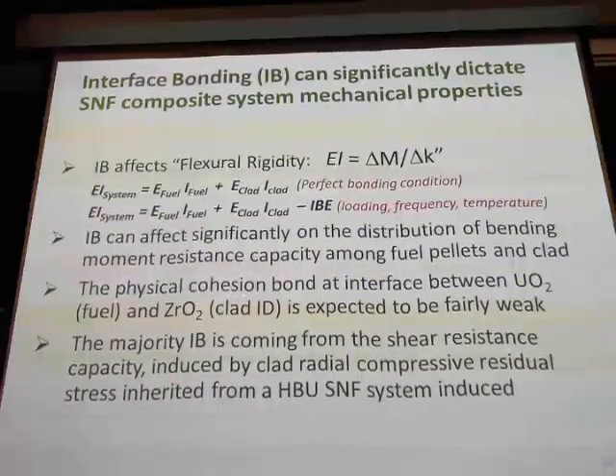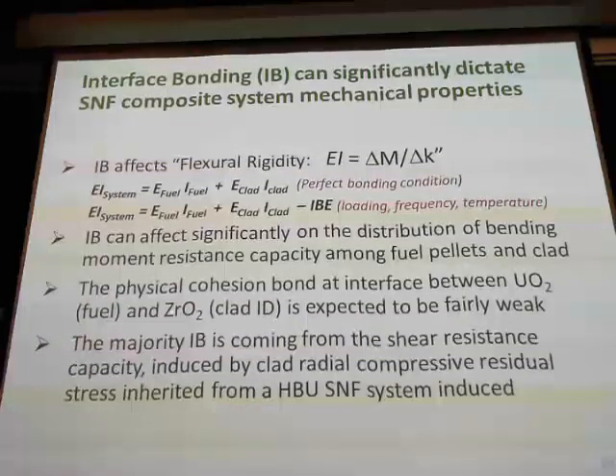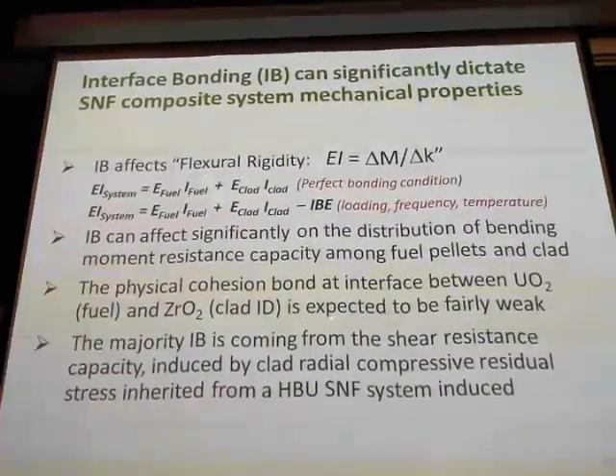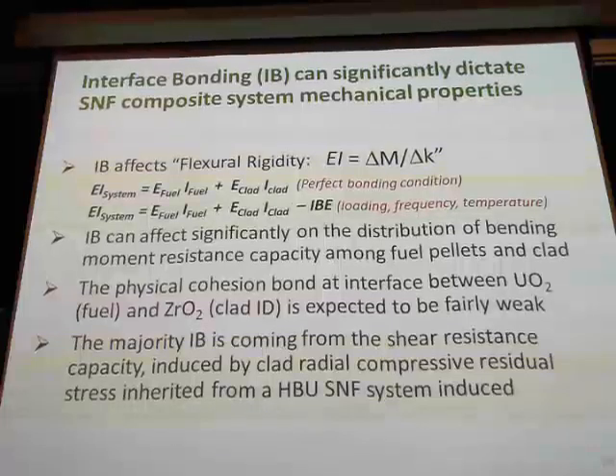And the physical cohesion bonding interface between the UO2 and the zirconium is expected to be fairly weak. And this is not just speculation, from some observation, the majority of the interface bonding is coming from the shear resistant capacity induced by clad radial compressive residual stress and inherited from the HBU SNF system. This gives you a better picture about it. You can see there is absolutely no gap.